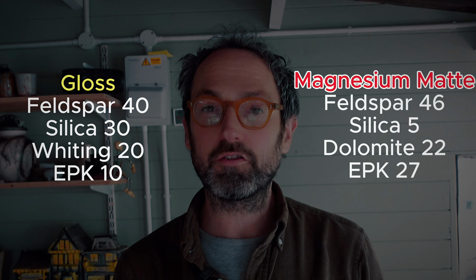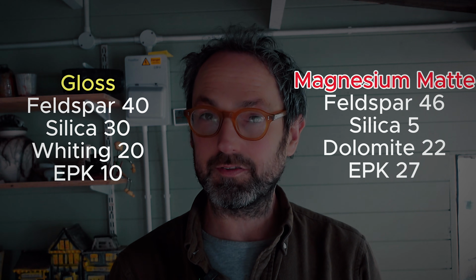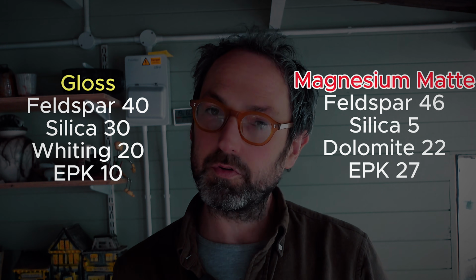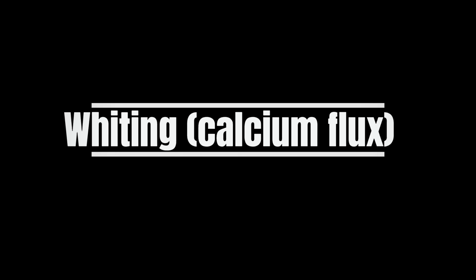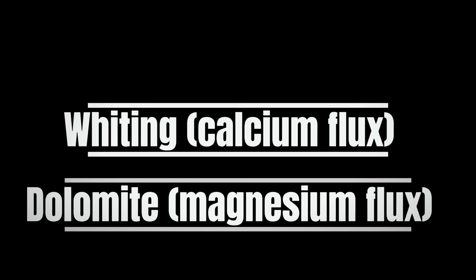We're going to just duplicate the glossy glaze, and then I'm going to show you how to edit the actual silica and alumina levels to push it more towards a matte glaze. And the other thing we're going to do is switch the whiting with dolomite. So we're basically going to switch it from a calcium-based alkaline earth flux to more of a magnesium alkaline earth flux. So it's basically the same recipe, we're just switching whiting with dolomite, and we're going to tweak the silica and alumina levels.